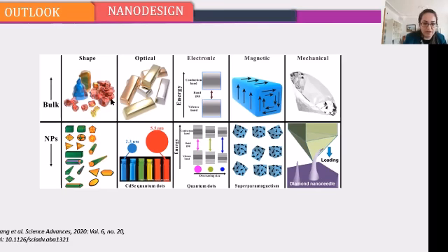Also, you are seeing here semiconductive cadmium selenide quantum dots, where the small size gives a blue fluorescence emission, while when it gets a little bit larger, to 5.5 nanometers, the color becomes red. The same happens for quantum dots.